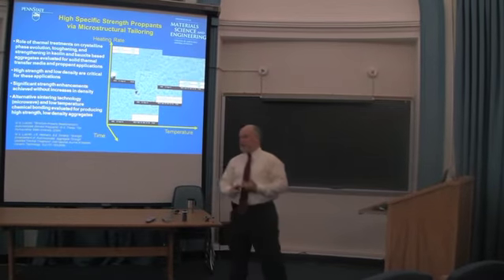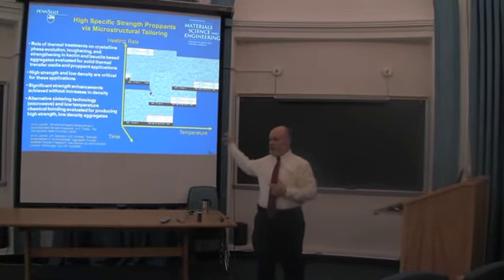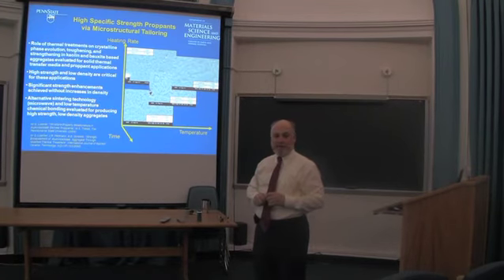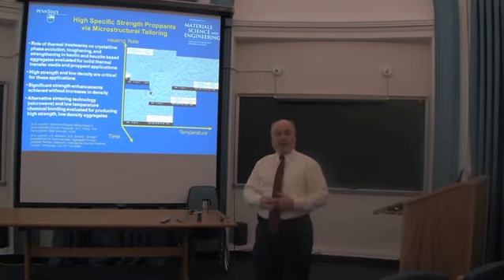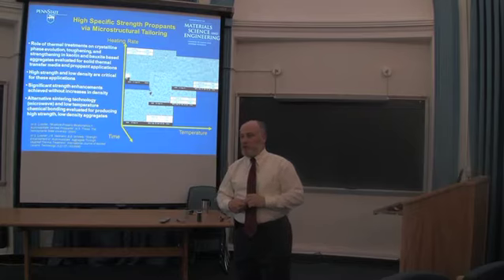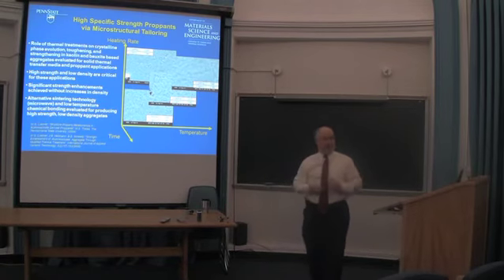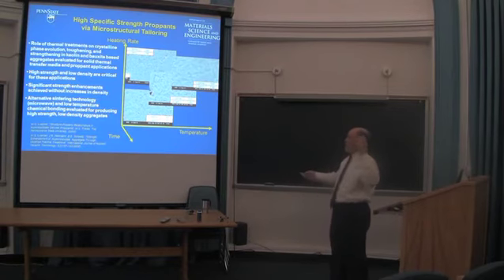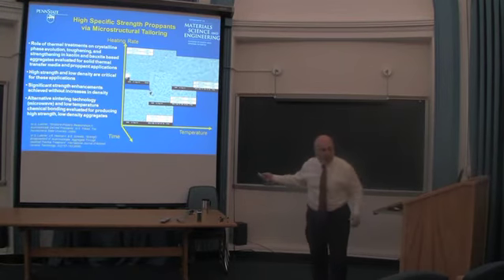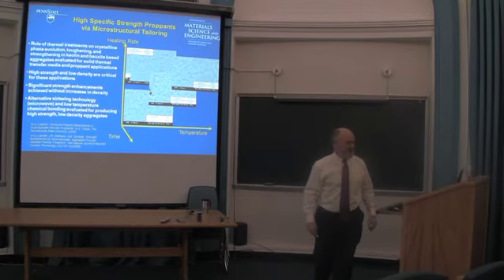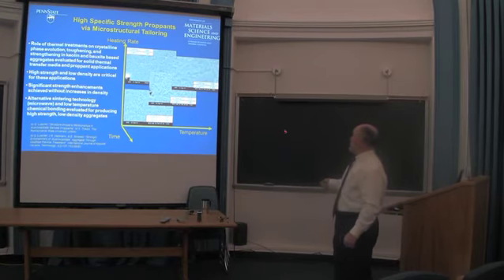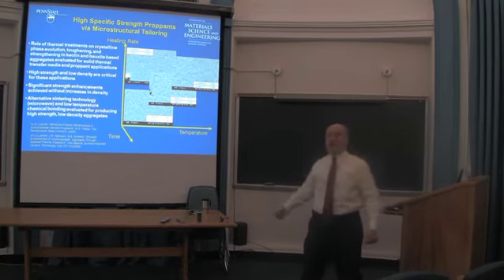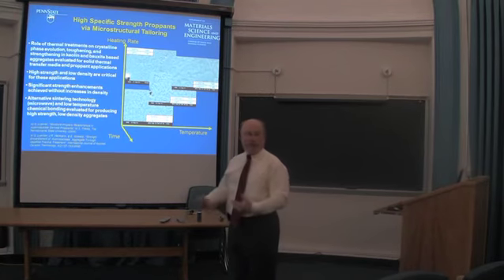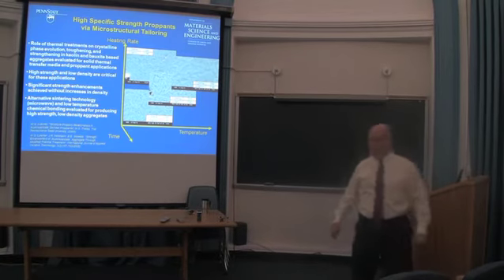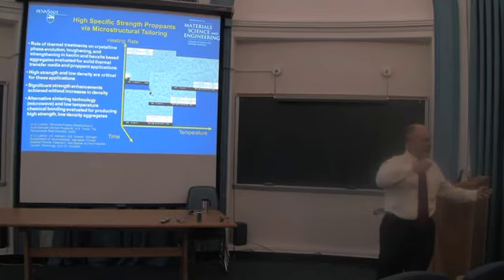We have to have the right crystalline phase assemblage. Cristobalite, a polymorph of silica, is a bad actor insofar as mechanical properties. You have to follow the crystalline phase assemblage evolution, the microstructural evolution, the density evolution, and all of these have a complex interrelationship in determining mechanical strengths. And what we found, and what this is showing now, is from rather mundane sintering temperatures and times. You're talking mundane being 1450 degrees C sort of range. That's the lower end. To over 1600 degrees C out this way. All right, heating rates from a few degrees Celsius per minute to 20, 40 sort of degrees Celsius per minute. So that's throughput through your cement kiln, okay?